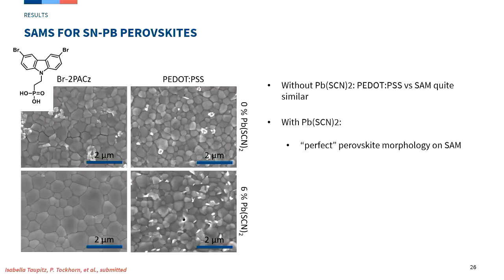Now, if we use the additive and the new molecule, you see a film like this—again an SEM top view image. It has very homogeneous, very large grains, so it's very good—almost a perfect film. You would think the solar cell made with this additive and this SAM is also very good.